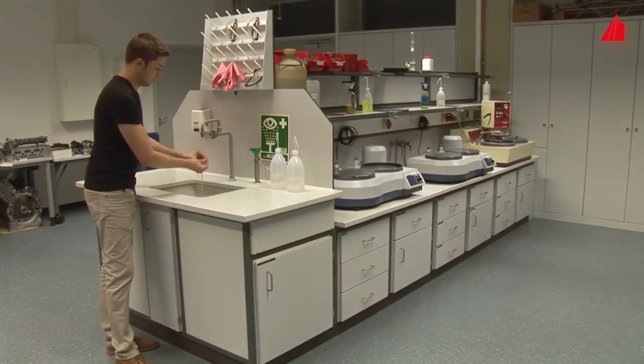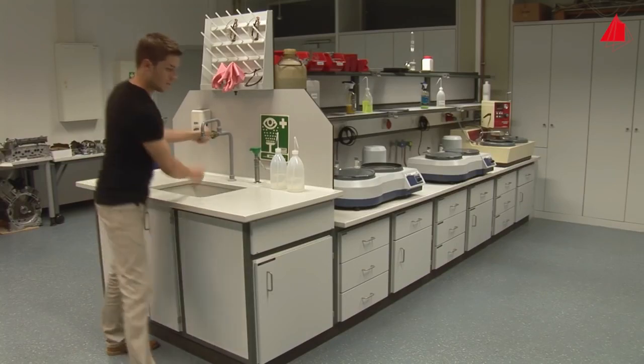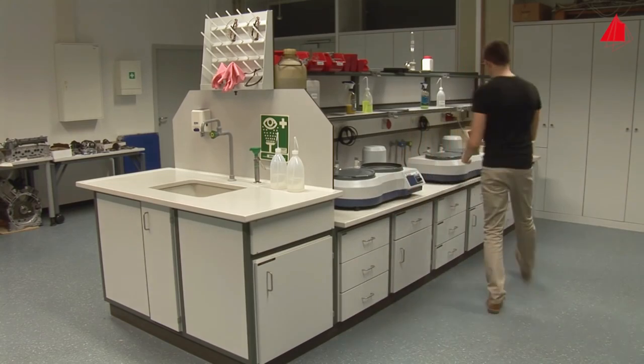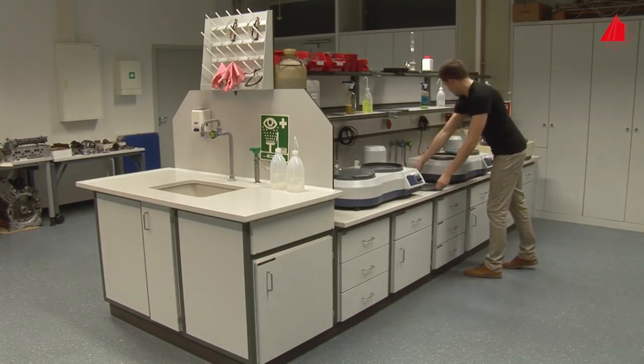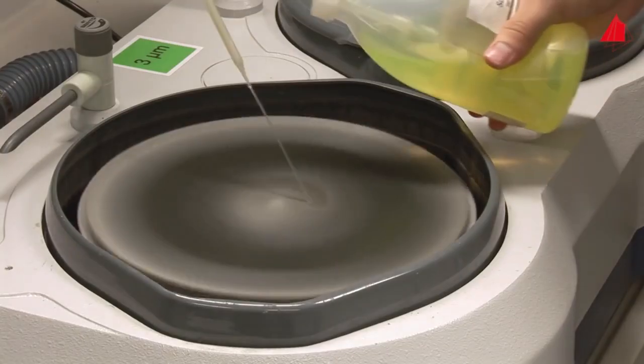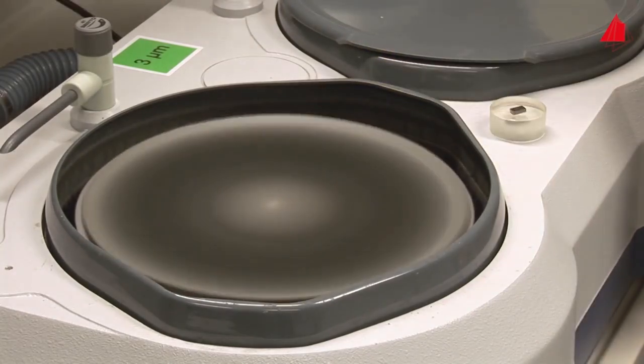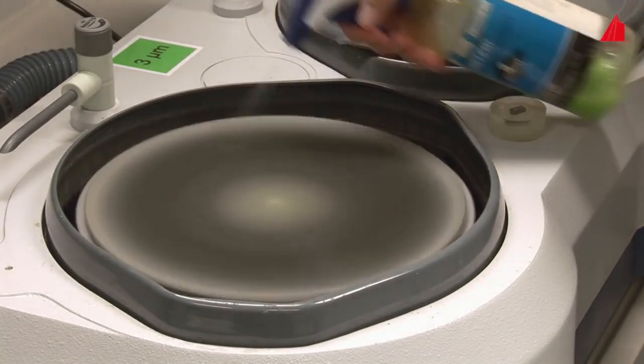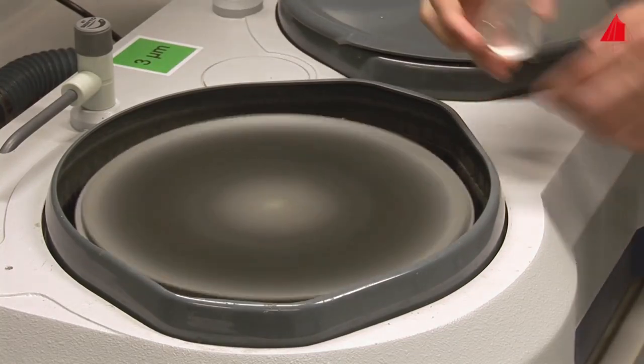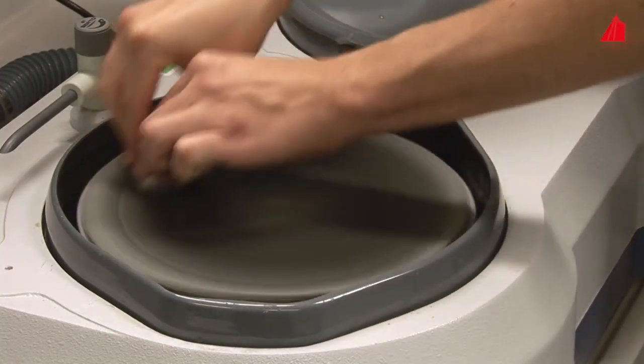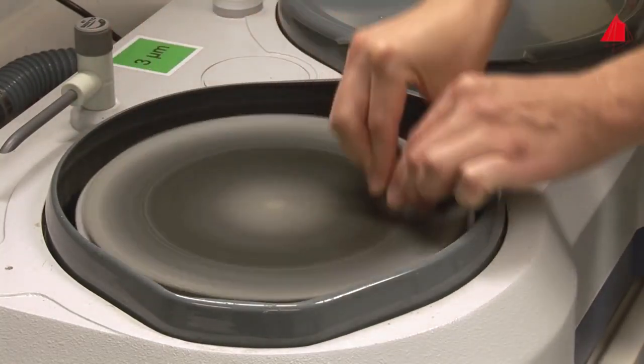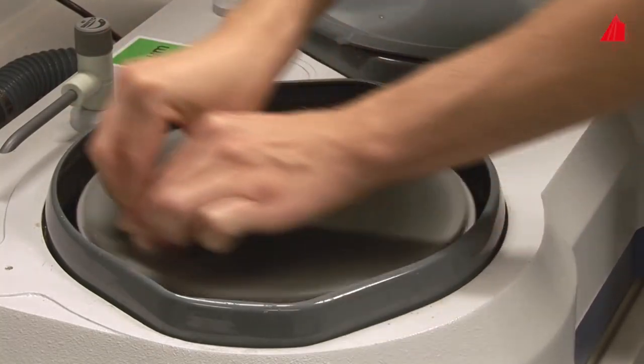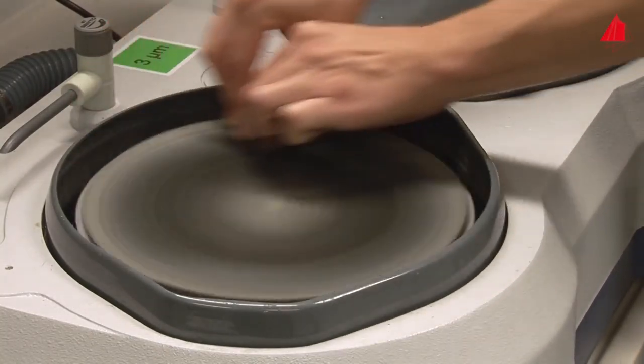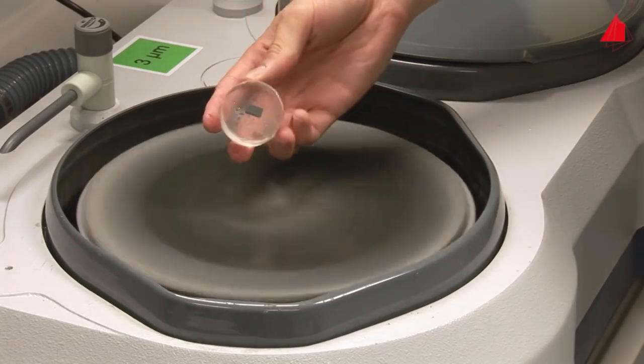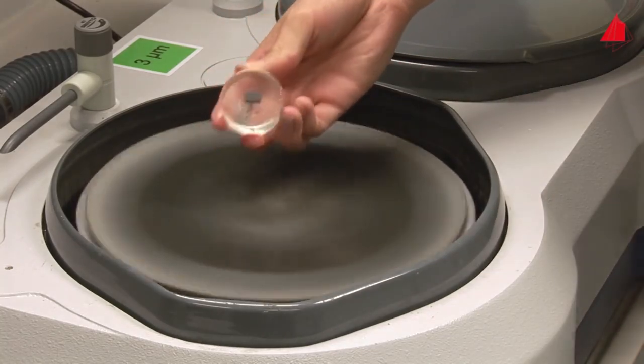To remove them, the material tester washes the specimen and his hands again very carefully and polishes the specimen for a second time. Now he uses a softer short nap polishing pad, finer diamond suspension of 3 micrometer particle size and less pressure. After the second polishing operation, the specimen surface has an almost mirror-like appearance. No more scratches can be seen with the naked eye.